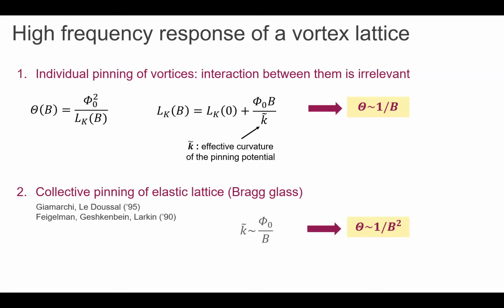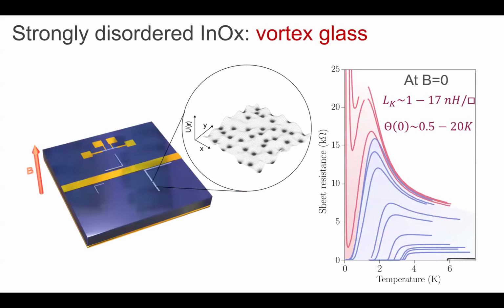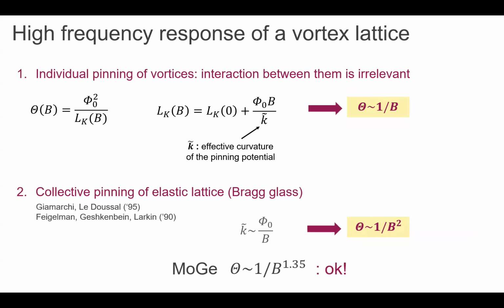There are other models, collective pinning, the elastic lattice, Bragg glass limit, and in that case, it is expected that the curvature of the pinning potential goes like 1/B. You plug that in, and you obtain something which is 1/B squared. And this is more or less okay with what we found in molybdenum germanium. So this molybdenum germanium is a good control experiment that shows that we can measure the superfluid stiffness of the vortex lattice. It's consistent with the standard pinning picture, and this is a very nice probe for the vortex system, which has, by the way, never been done in that configuration so far.